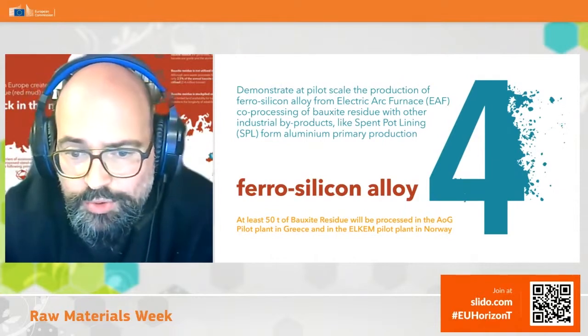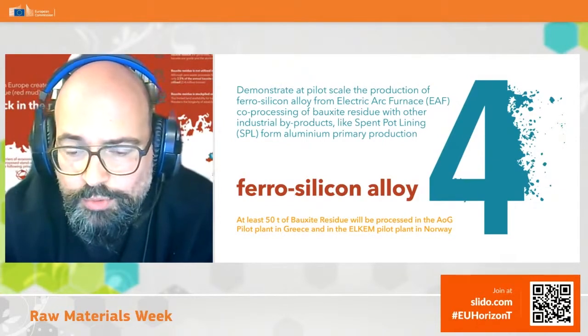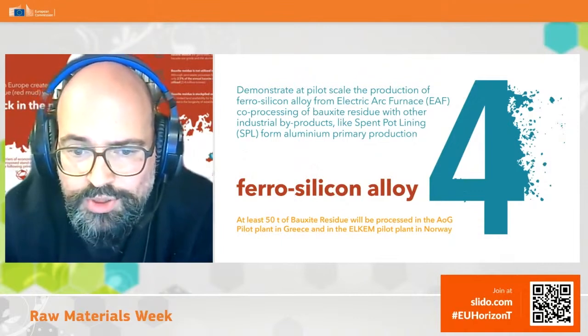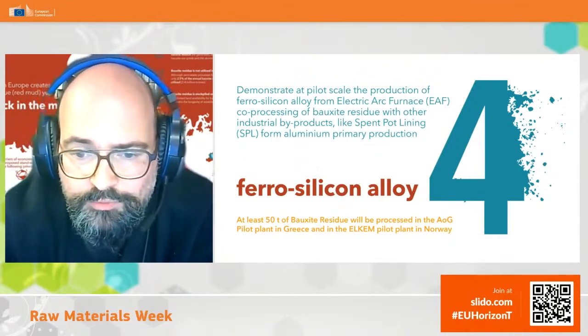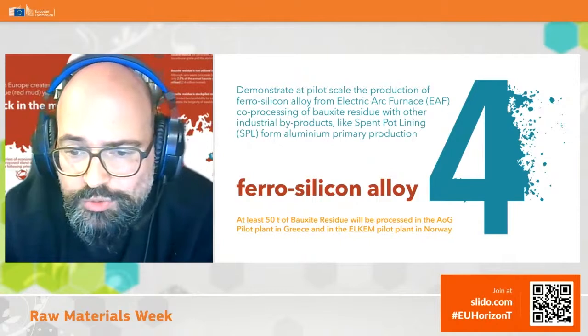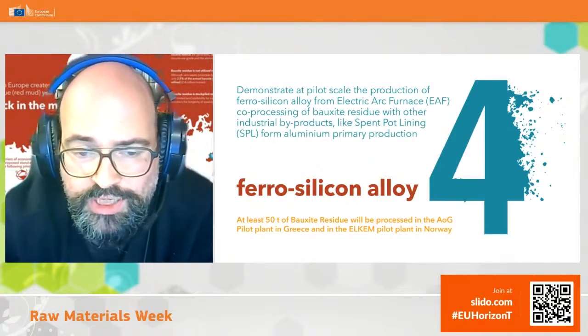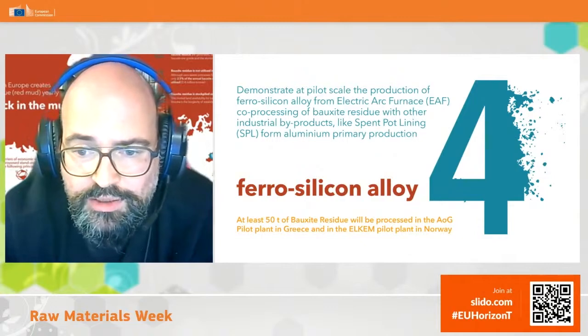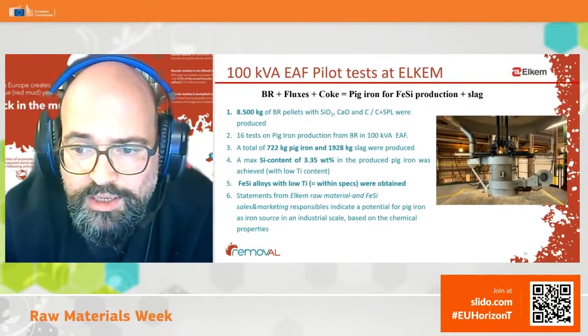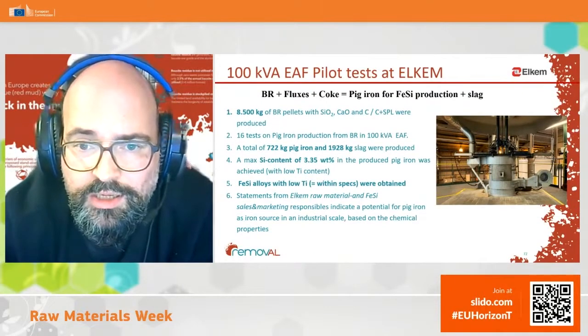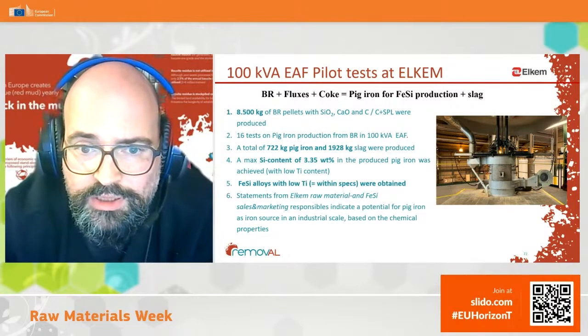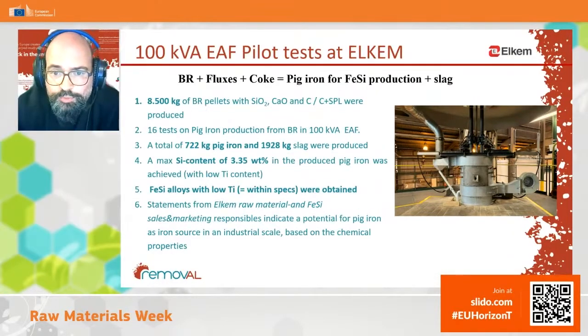Then the next major task, work package, if you want, in our project was to extract iron from the bauxite residue. Bauxite residue is 40 to 50% iron oxide. So next slide. Elkem in Norway did a pilot test in extracting the iron in an electric arc furnace in order to produce ferrosilicon and slag.